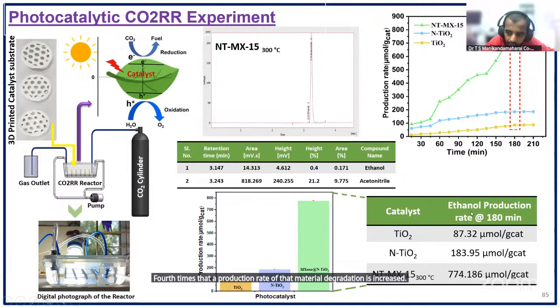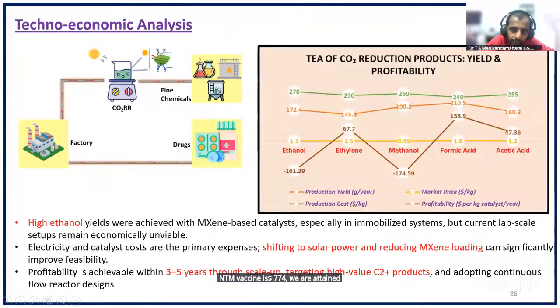The ethanol production rate in TiO2 is 87, and in NT MXene we attained 774 per gram of catalyst. In the techno-economic analysis, high ethanol yield was achieved with MXene-based catalyst, especially in an immobilized system, but current lab scale setups remain economically unviable.